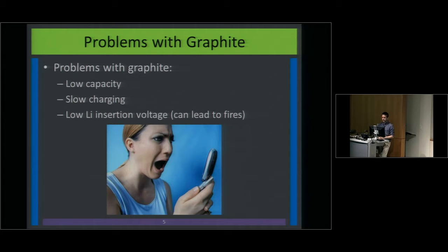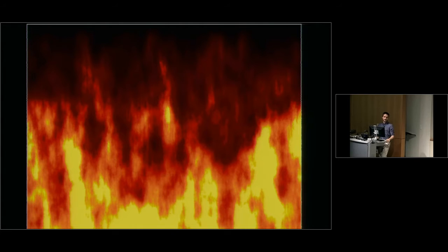On a more technical side, graphite has a really low lithium insertion voltage. This means it gets really close to the potential of lithium itself. And so lithium can start growing on it and form needle-like dendrites, which pierce the separator, cause a short, and that can lead to fires, which we've seen in the news and is very bad.